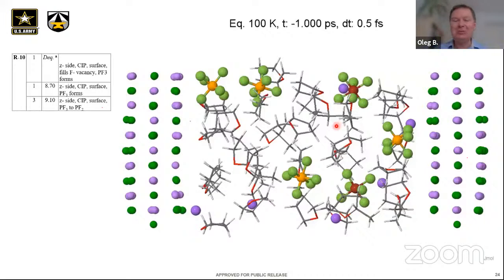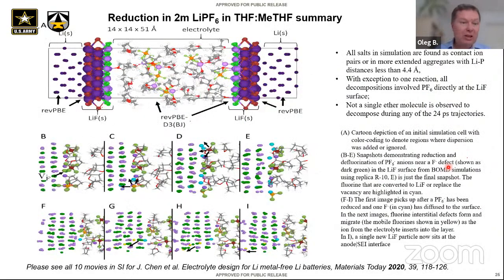You can go watch all 10 movies if you're interested and see that indeed for R10, there is another interstitial fluorine. But I can show it to you also on this picture for another replica. Look, that's the fluorine, which is more in cyan, just so you can see it, which is available. It's going to come, and as it's coming and wants to replace another fluorine, which is already in a 3rd layer from the lithium of the SEI. Once it's approaching the fluorine, we color the other 2 which participate in this simultaneous transfer, right? In yellow, right? So once it's coming in, another fluorine from the 1st layer gets kicked out.